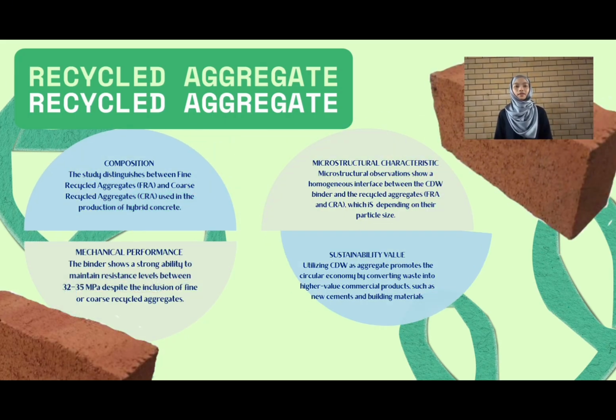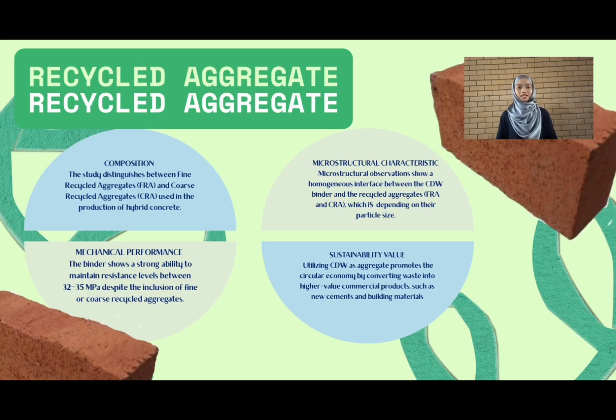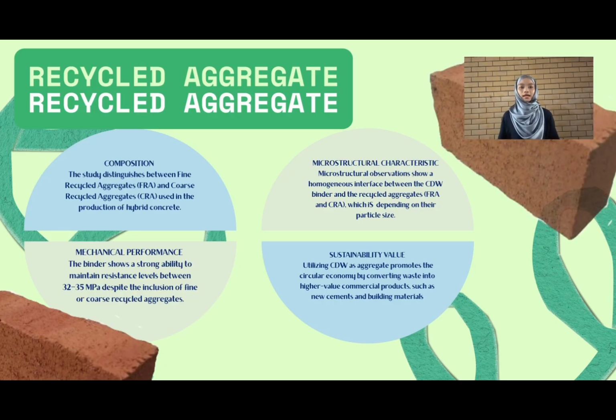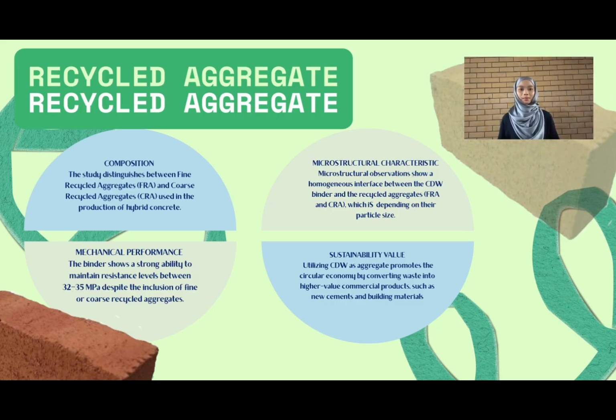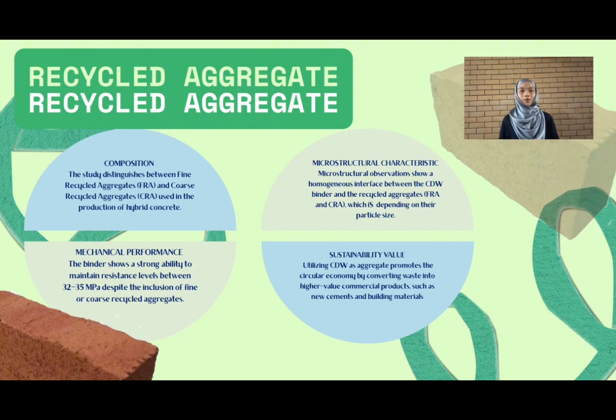When we look at the results, the study highlights a clear distinction between the use of fine recycled aggregates (FRA) and coarse recycled aggregates (CRA) in hybrid concrete. A key finding was the microstructural characteristics of the material. We observed a homogeneous interface between the CDW binder and the aggregates, which is heavily dependent on particle size.